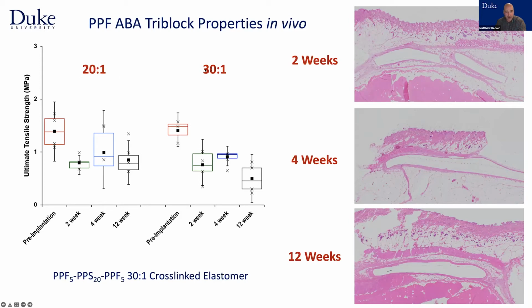So this is more heavily cross-linked. This is lightly cross-linked, so those mechanical properties are changing with time. And the rate of change is critically important to that remodeling process. While it's working so far, according to the computational models developed by Alison Marsden and her colleagues, the flexibility in the 3D printing structure is really what's enabled this to advance as far as it has.